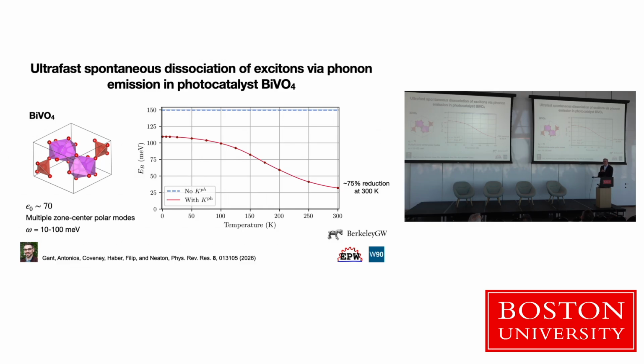And so you might think, well, I'm going to have a lot of recombination. I'm not going to be able to separate the electron and hole. But it turns out with the approach we're using, we can predict that there's a large reduction in the binding energy at room temperature into a range which is more suggestive of where you might imagine that separation is more probable.